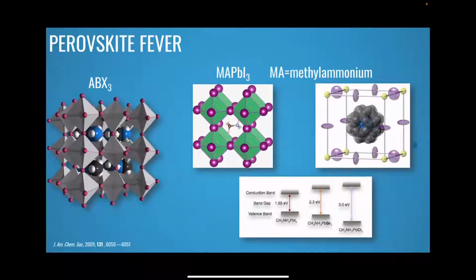And the crystal structure is a normal perovskite, where, however, the organic cation is at the center of the cubic-tetragonal unit cell and is highly mobile. The fascinating aspect of these materials is that they are very tunable. For example, if you just change the halide from iodide to bromide and to chloride, you can modulate the band gap of these materials. Anyway, in 2009, in this seminal paper, the authors prepared a Grätzel cell, solar cells, by using this semiconductor as active layer.